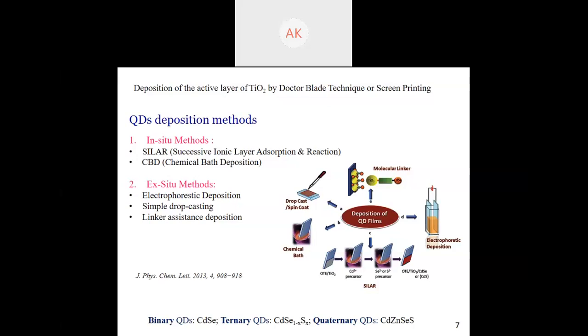Ex situ methods are when you have already synthesized the quantum dots previously by a hot injection method or a hydrothermal method, and then you deposit them over the metal oxide, maybe TiO2. You do electrophoretic deposition, or simple drop casting, or linker assisted deposition. Now for ex situ methods, there is good control over the size and dimensions of the quantum dot as opposed to the in situ methods.